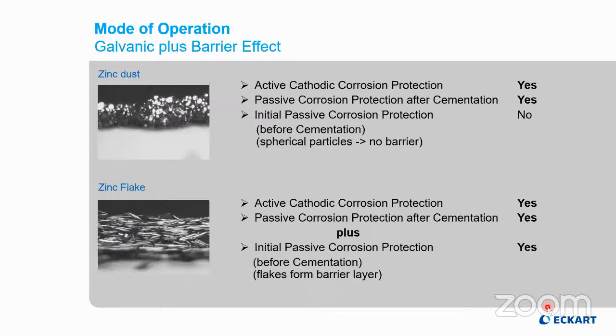Here, as a summary, the mechanisms of the corrosion protection. With zinc dust, you have an active corrosion protection through the galvanic properties. You have a certain passive corrosion protection because of the cementation process. Similar with the zinc flake, but in addition, because of the zinc flake layer formed, you have an additional initial passive corrosion protection. We have called this the two-in-one concept because by using zinc flake, you get initially an additional corrosion protective performance by the barrier layer formation.